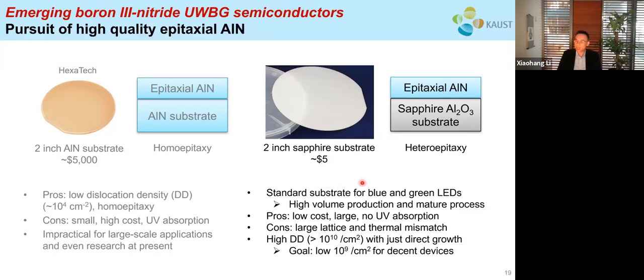However, it has its own drawback as well, because they are two different materials. They have the so-called large lattice and thermal mismatch. This large mismatch can lead to a high dislocation density, over 10 to the 10 per centimeter squared. But we do not necessarily have to go to 10 to the 4. We just have to hit about low 10 to the 9 for decent devices for many applications.